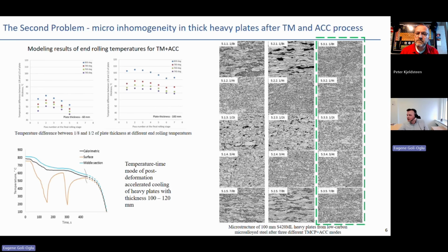Here, for example, is an example where you see, for a person looking in an optical microscope, it's obvious: condition 1 gives certain non-uniformity, condition 2 gives certain uniformity, but if you reach the optimal connection between chemistry and technology and the process regimes, then you could get a quite nice uniform fine-grained microstructure, and this is what we are aiming for.